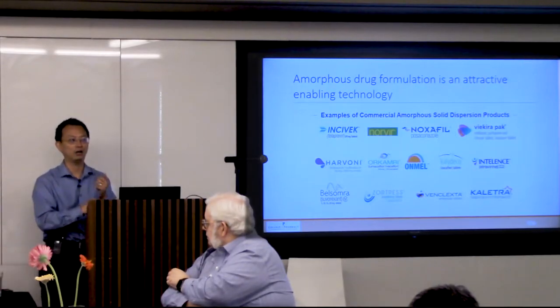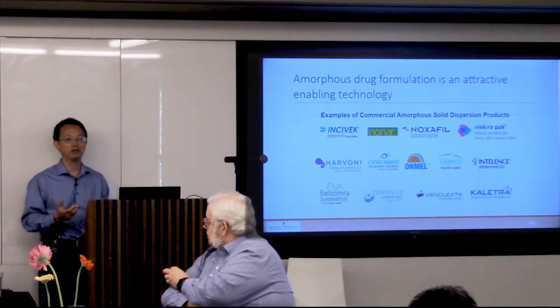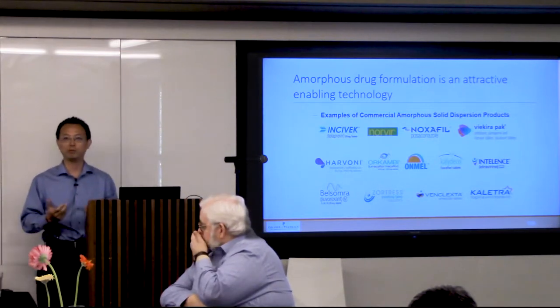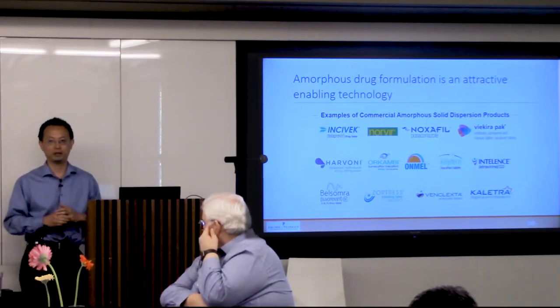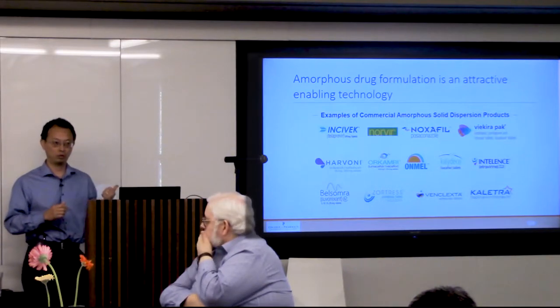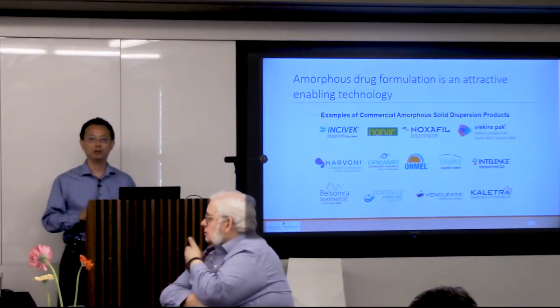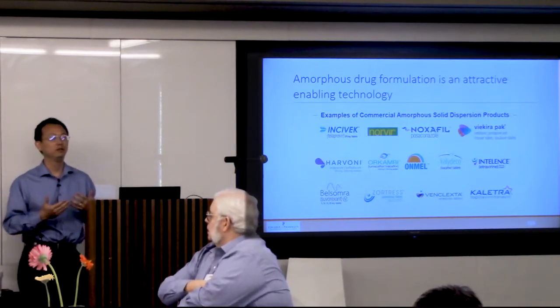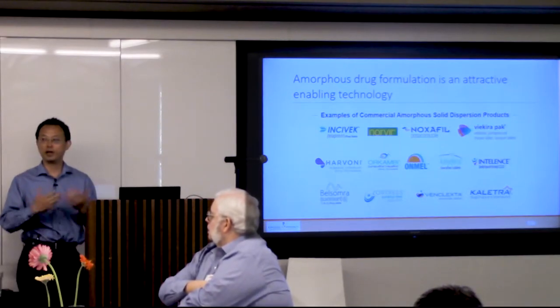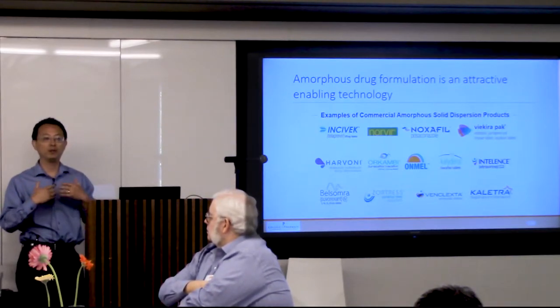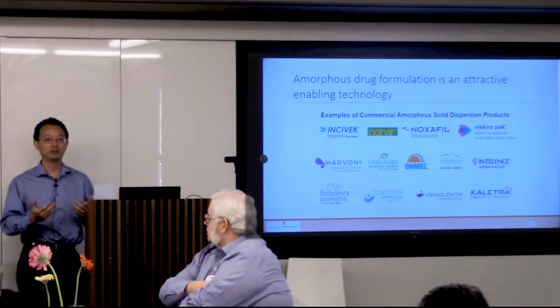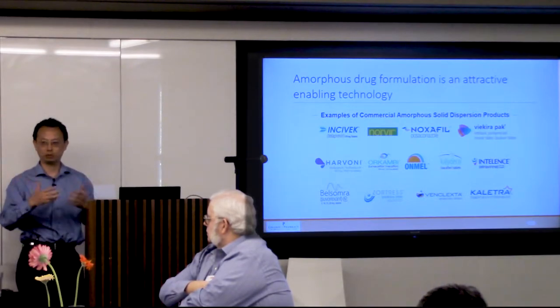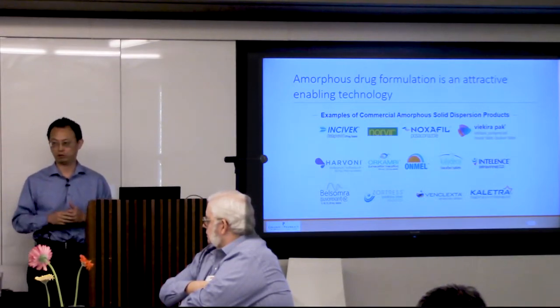So many years ago, nanoparticles were really hot. But one of the issues when you make nanoparticles is that once you put them in a dosage form, it's very hard to disperse the nanoparticles back. Extrusion is the opposite. You actually make a glass, so you can store them and handle them. But then when the water hits those glasses, the drug will supersaturate and precipitate out. They actually form nanoparticles.